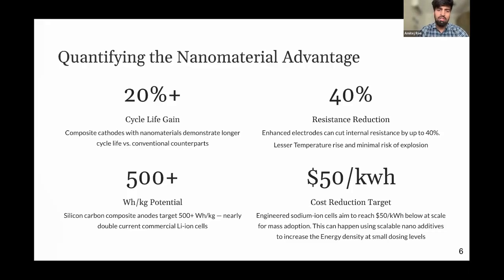We are aiming for more than 500 watt hour per kg potential of energy density. And how would that be possible? The current chemistry will not allow that to happen. So we need material innovation, as I mentioned, with silicon carbon composites and using solid electrolytes, shifting from the conventional liquid ones. We are aiming to get this 500 plus watt-hour per kg, which means the current range that you're getting out of your EVs is going to be double, just double. So imagine a vehicle where you get 2 years more life and double the mileage per charge, and all this with a cost reduction target, not at a premium price.